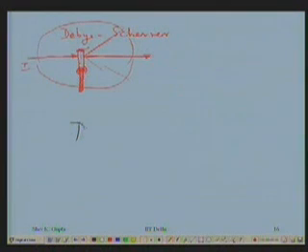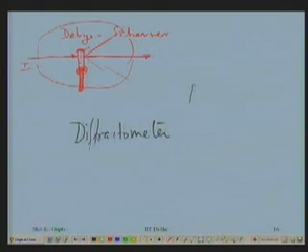Or else we use a diffractometer. Again, there is a powder specimen. This powder specimen is kept in a rectangular cavity made in a metal plate. In this cavity you fill the powder, and then on top just simply spray some Teflon or any other plastic which will keep it together, not let it fall, and at the same time will not give rise to any diffraction. Right. Now let's look at the geometry of this diffraction.